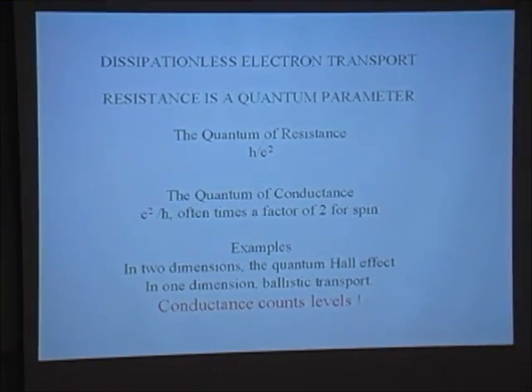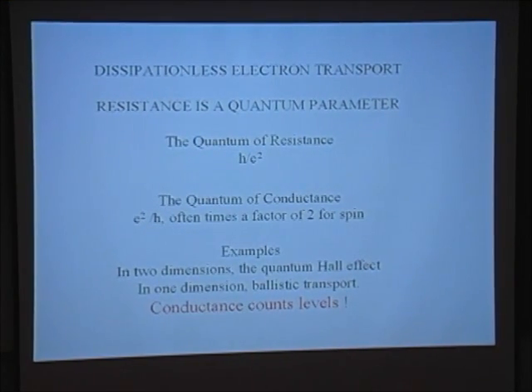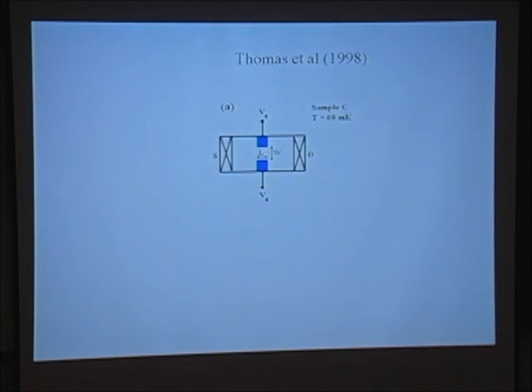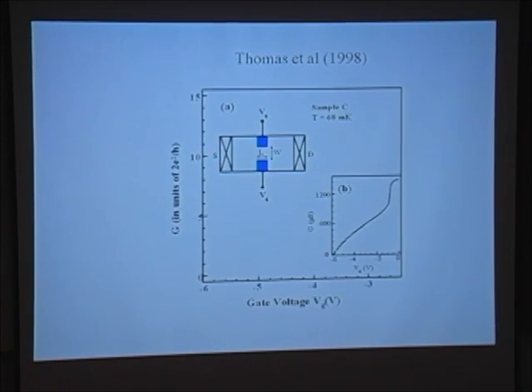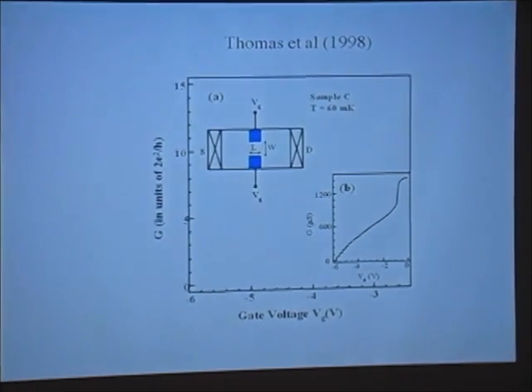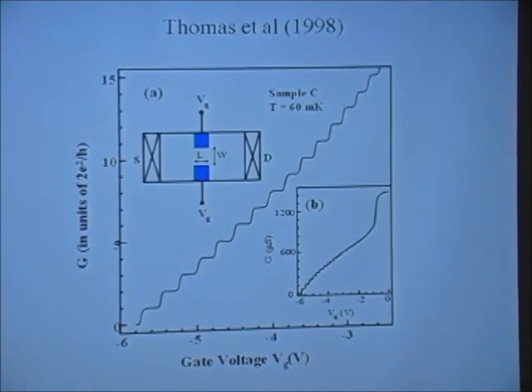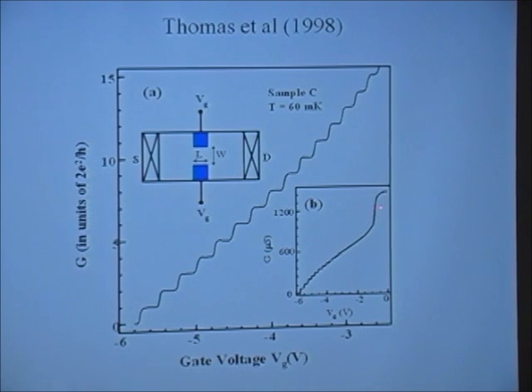So what the conductance does, actually, is count levels. Before we discussed resistance, h over e squared, but if we say it's e squared upon h, times a factor of 2 for spin up, spin down, then if we measure a conductance of 2e squared over h times N, that means we have N levels, and so we can count the levels. And this is what we do in the experiment. So this illustrates what happens. See, we turn this on.